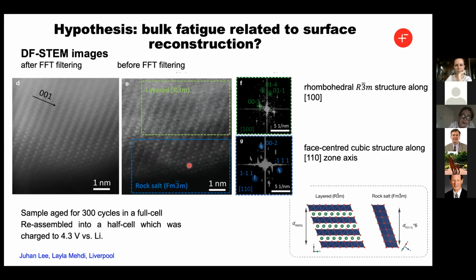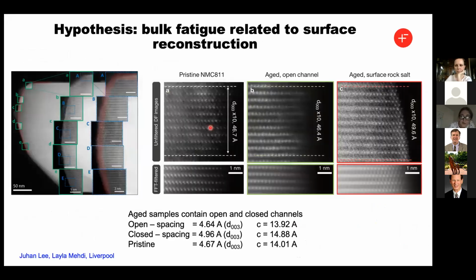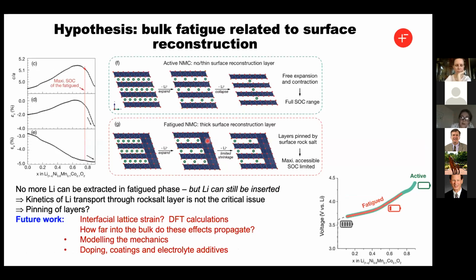By doing some very careful electron microscopy, in collaboration with Layla Mehdi from Liverpool and her group, we were able to look at the registry between the rock salt phase and the layered phase and see that the registry of them is exactly perfect when this material is fully expanded. So if you look at the 75% state of charge, then the spacings between the rock salt and the layered phases are almost exactly the same. And so what we think is going on is a curious mechanism where the surface is pinning the structure, and so it prevents that collapse of the layer, and the further removal of the lithium would then require this layer to collapse. There are a lot of issues of interfacial strain that we need to work out, and we need to think about how these surface phenomena propagate into the bulk. But we don't believe it's a simple impedance thing. We believe there's a surface pinning effect.